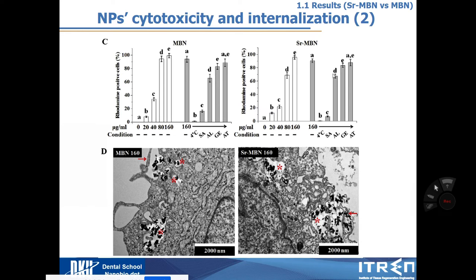And then this is not the only way to check nanoparticle uptake. I want to look at it with my own eyes, so I used bio-TEM to check nanoparticle uptake by the cell. When you look at the asterisk, you can see some black dots, which are nanoparticles. They are being uptaken by the cell.